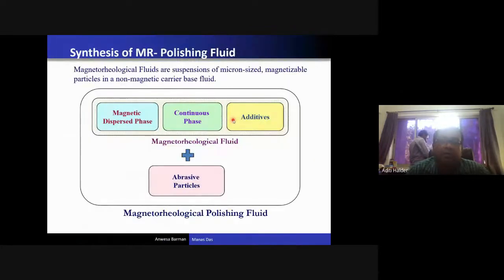Okay, so if you want to generate this MR fluid indigenously, there are three phases. One is the continuous phase, which is the base material. The second part is the magnetic dispersed phase, and the third one is the abrasive particles. As I have already told, the continuous phase consists of a water-based or oil-based media. This base media is mixed with ferromagnetic iron particles in the micron size. The size depends on your actual requirement. If you need a higher magnetic field, you have to use bigger size iron particles.